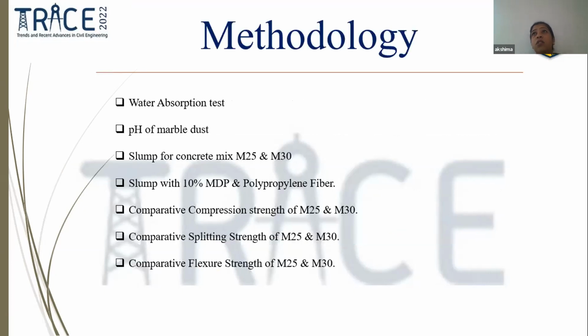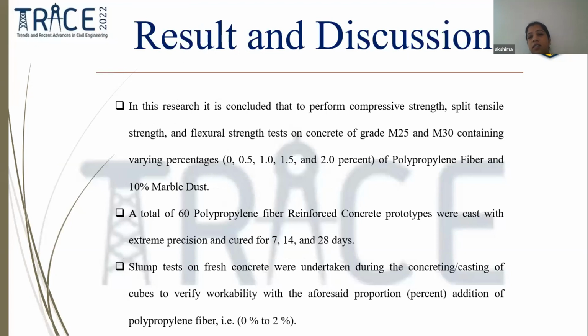Okay, methodology. What methods have we used to check all the strengths and compare with the two basic concretes? First is the water absorption test, to check what amount of water we have in the mix. Second is the pH of marble dust, because we have taken marble waste, which is a powder, and replaced it at a percentage of 10. Slump for the concrete mix with both M25 and M30. Slump again after adding 10% marble dust powder and polypropylene, so that we can check the workability. Next, comparatively, compressive strength of M25 and M30, splitting strength of M25 and M30, and flexural strength of M25 and M30.